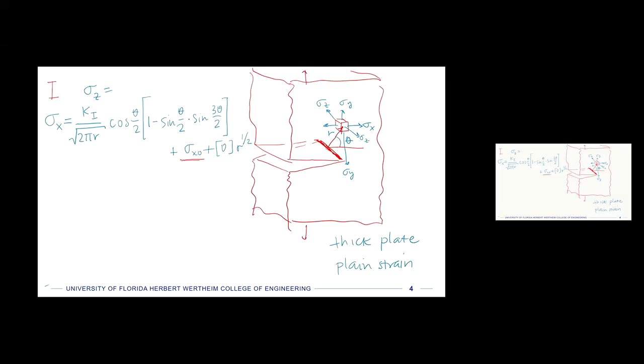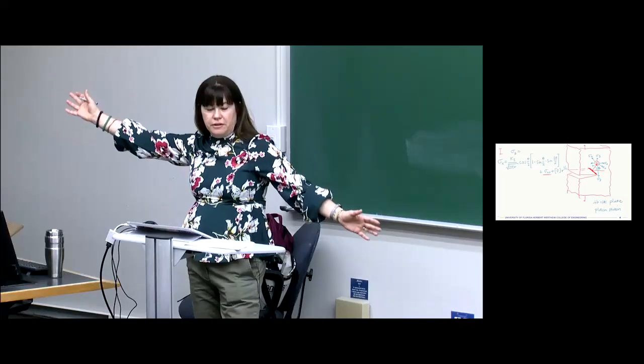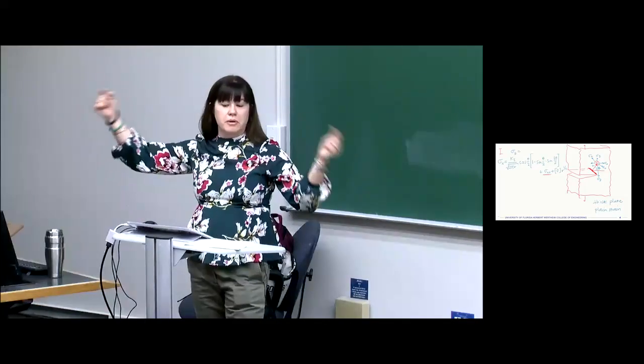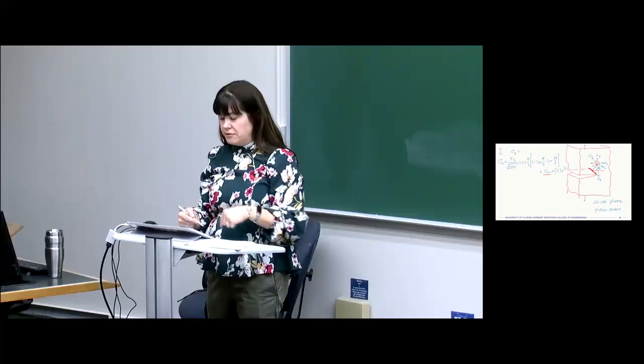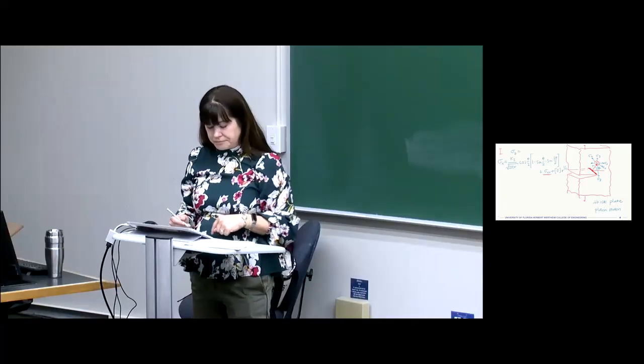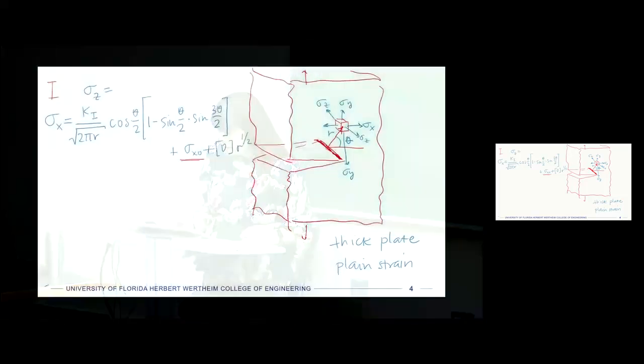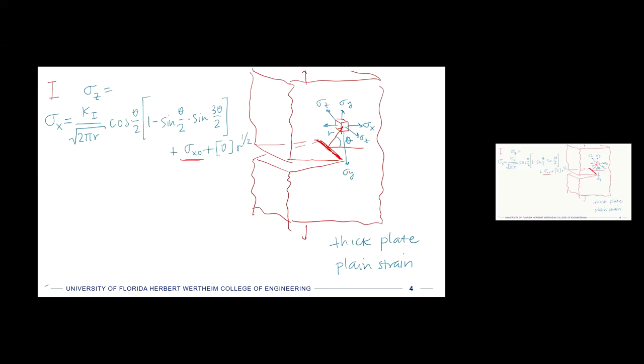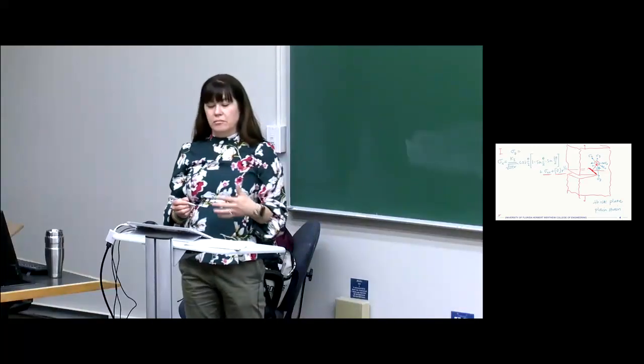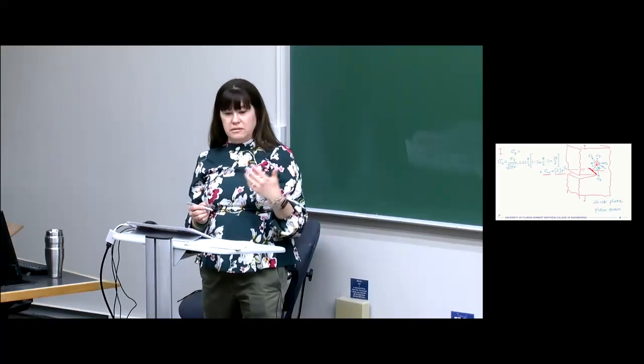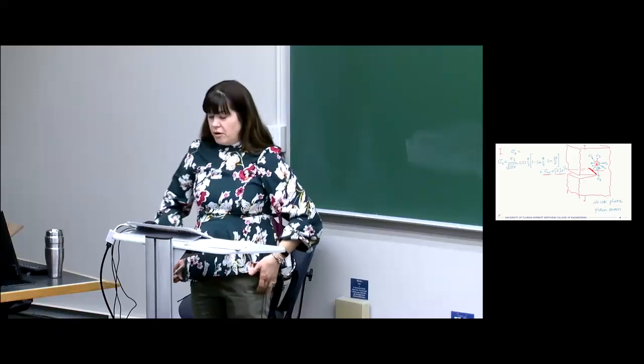And so this would be like if we had any stress in the far field that was affecting it. That would be superimposed onto the local stress that we have near the crack tip. And then we have another term here that is a weird notation, but it's the order of r to the 1/2. So that means like, is it single microns? Is it tens? Is it hundreds? Is it whatever? So how far away are we?